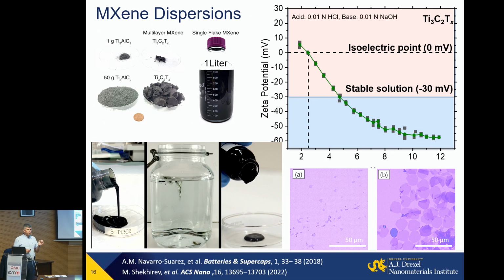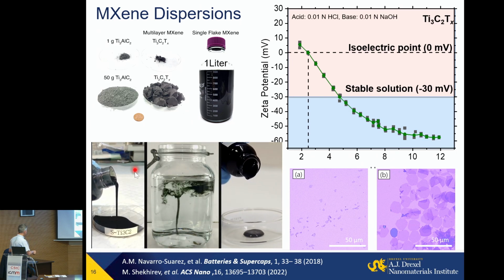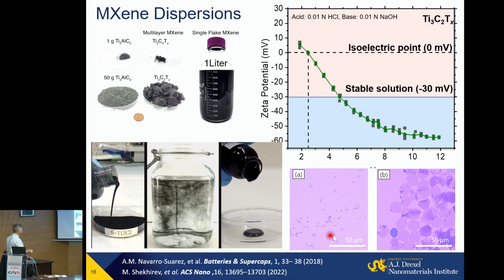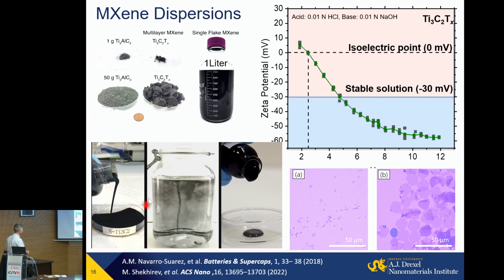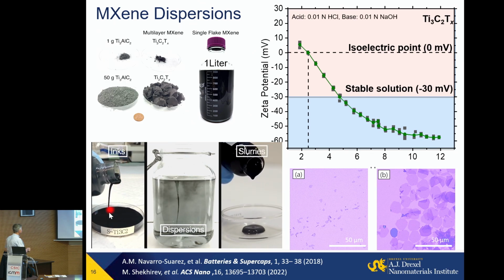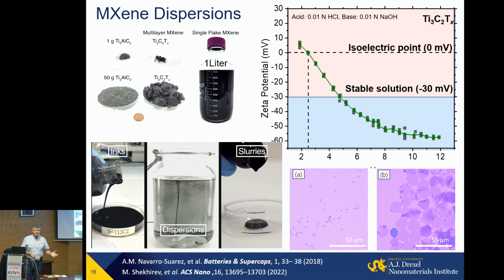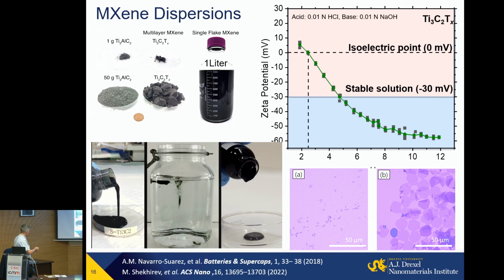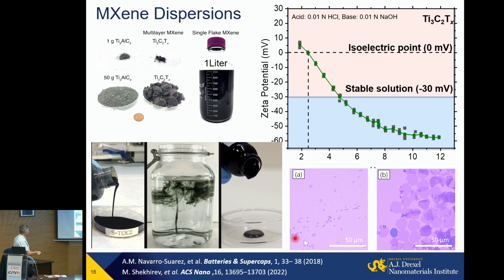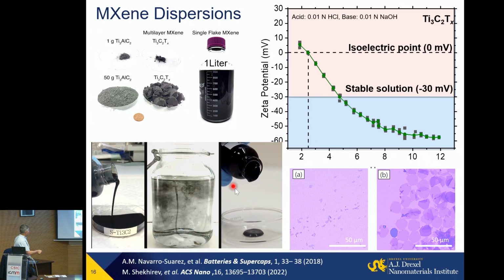And that's again very, very important if you think about green processing, inks. You don't have binders and surfactants that you need to burn afterwards, and sometimes it can be very toxic. You can just disperse material, and depending on particle size, for example, smaller particles will form, at the same concentration, a much less viscous solution, 5 to 10 milligram per milliliter. This ink we can use, for example, for inkjet printing, spray coating, dip coating, spin coating.